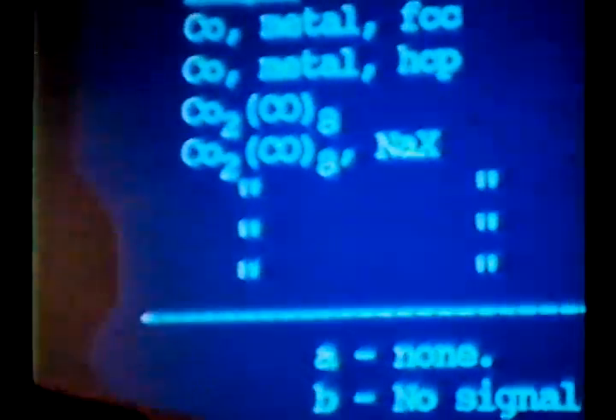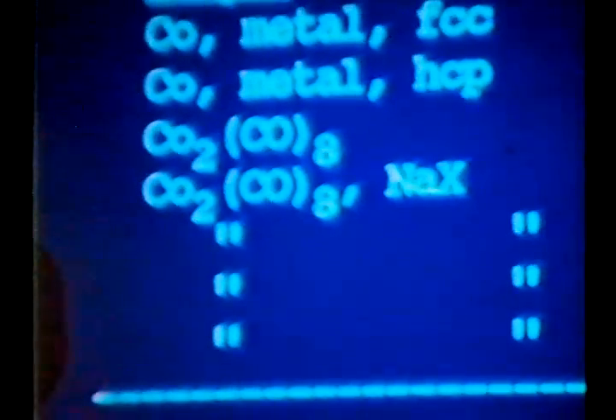But what do we see, and why is it so useful? Cobalt metal in a face-centered cubic structure, not treated, has a signal of 219 megahertz. Hexagonal close-packed cobalt, on the other hand, has a signal of 230 megahertz. So potentially we can get the structure of the metal particle in this experiment by measuring the frequency. That's very difficult to get from ferromagnetic resonance and lots of other techniques.